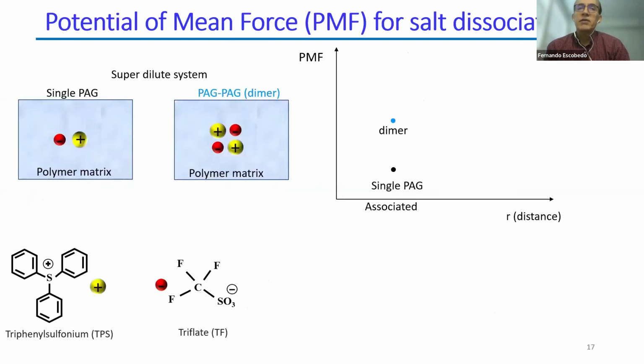So one of the main tools that we wanted to use is the potential of mean force for salt dissociation. The key idea is that you have a super dilute system where you have, say, only one salt molecule or two salt molecules in the polymer medium. Then you want to see how the free energy of this system changes as you change the distance between these moieties. For example, in this plot I have the PMF, which is a free energy. For the single PAG, this corresponds to the free energy for the associated state, and this will be for the case of the dimer, so this case over here.